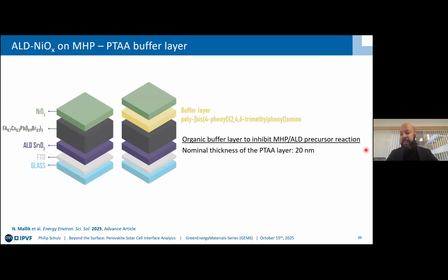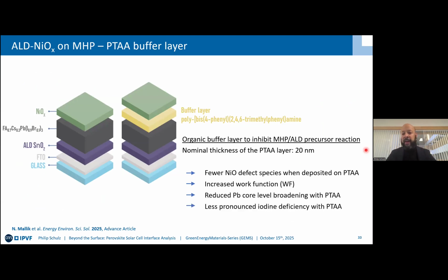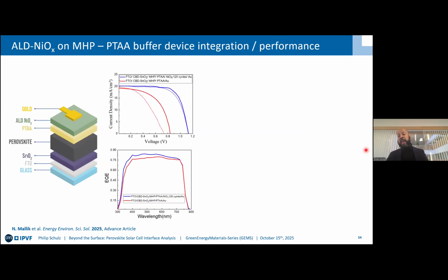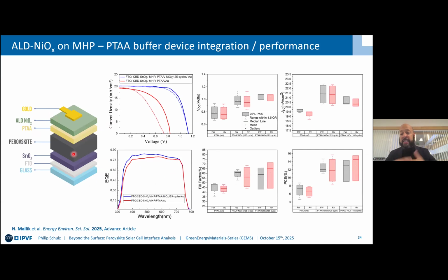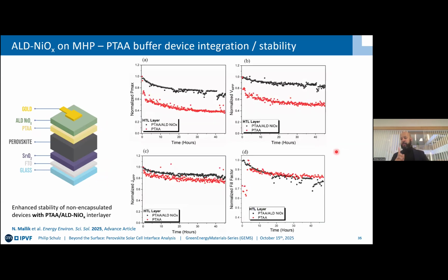And yes, using a thin PTAA layer, we found fewer defect species in nickel oxide, an increase in the work function, the lead core level broadening reduced, and also the iodine deficiency was not as stark as before. So this then made it into some prototypical devices, not a real HTL, just the thin PTAA layer and ALD nickel oxide, no passivation whatsoever. But in this configuration, we still get some results and some working devices that go a bit beyond what we had with the PCBM buffer tin oxide, for instance. And this was an important part.